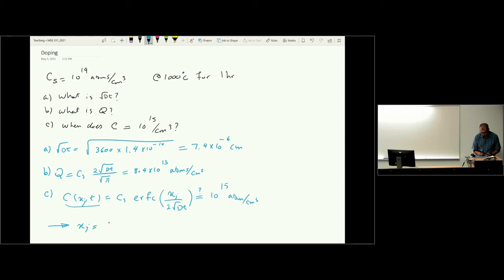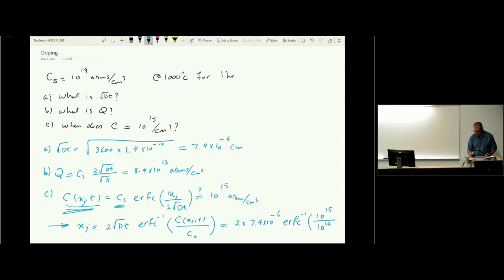So xj is 2 square root dt times the inverse of the complementary error function of c of xj and t divided by cs. I already have the characteristic diffusion length, so this is 2 times 7.4 times 10 to the minus 6 in centimeters, times the inverse of the complementary error function of, at that depth, the concentration has dropped to 10 to the 15 atoms per centimeter cubed. My surface concentration was 10 to the 19 atoms per cubed. So this is 1 over 10,000.